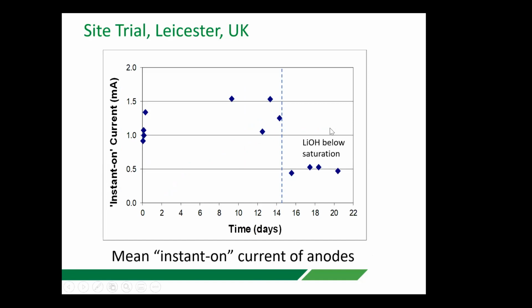The fact that the lithium hydroxide saturation was lost was also seen by another parameter that we were measuring. And this was after the 24-hour period when we disconnected the anodes. At reconnection, we would measure the current output of the anodes within 5 seconds of reconnection. That tells you indirectly the power that remains in the galvanic anode. And obviously the first 14 days or so, that was well above 1 milliamp per anode. But suddenly after about 14 days, that dropped significantly down to about half a milliamp. And that coincided with the time when the lithium hydroxide had been consumed and the pH started to drop.